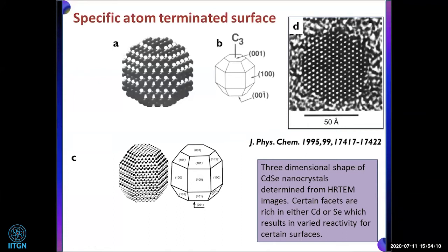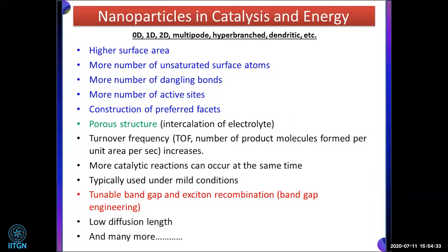If we make other crystal catalyst nanoparticles, for example cerium oxide, iron oxide, molybdenum oxide, anything, with the preferred facets, where one surface has specific terminated atoms, that will give us huge reactivity. And the other thing is the porous structure, which I have already shown in the cerium oxide nanocubes. That is a big nanocube of 90 nanometers, made of small 6 nanometer nanocrystal building blocks. That gives us a lot of pores, and more pores mean all the inside active sites are accessible to the reactant.